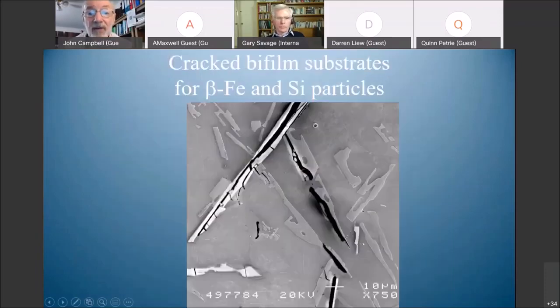Okay, and then of course you remember that on the backs of bifilms we get precipitates. This is an aluminium silicon alloy, but these things happen in steels and nickel base. They happen all the time. The precipitates form on bifilms. Interestingly, for those metallurgists amongst you, precipitates don't form on grain boundaries, I've concluded. They only form on bifilms. So the precipitates appear to form on boundaries, but only when there's a bifilm in the boundary. So, there it is. I don't know whether that's true, but I'm pretty sure it's true.